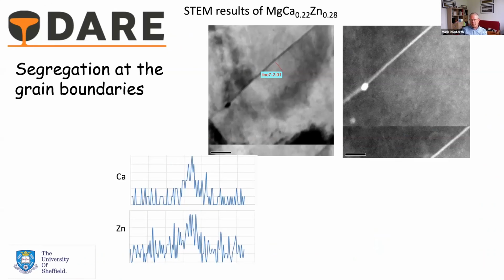And the trick here is the calcium. It's a large atom relative to the magnesium. It segregates to the boundaries, but it does play pretty much exactly the same role as the rare earth elements do in terms of forming that crystallographic texture.